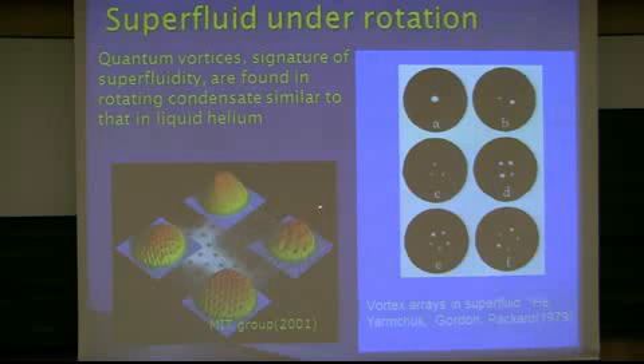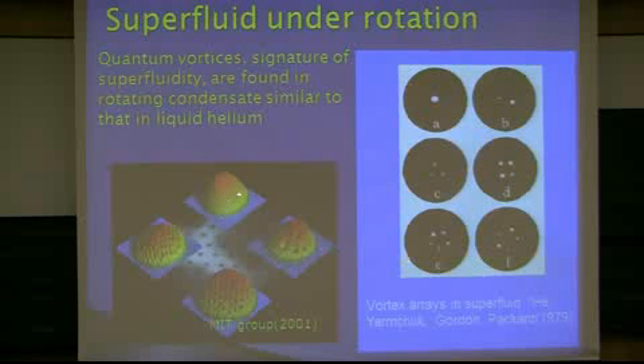When you increase the rotation velocity, this density minimum corresponds to the vortex core, meaning normal. When you increase the rotation velocity, the number of quantized vortices increases and eventually destroys the superfluidity. Similarly, in helium 4, depending on the rotation speed, you have a single core, 2, 3, 4. They did the experiment almost 13 years ago or something like that.